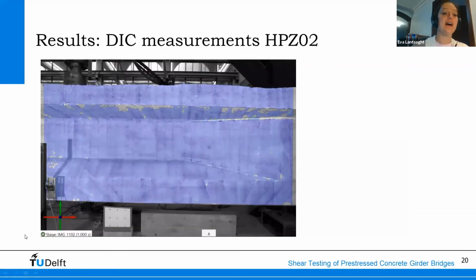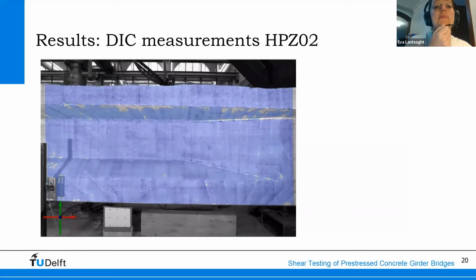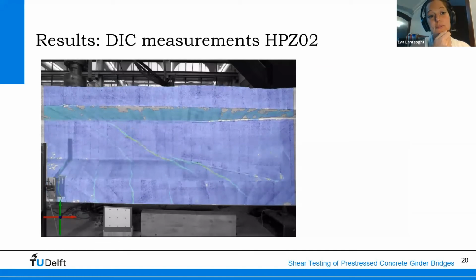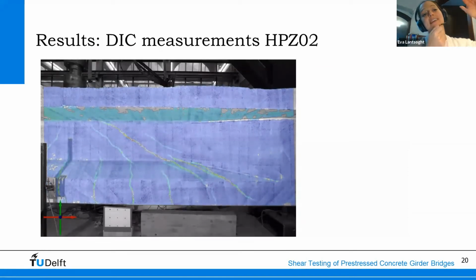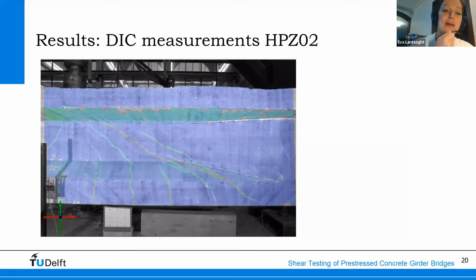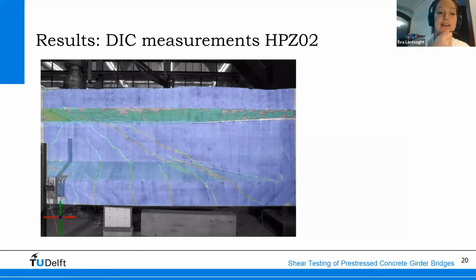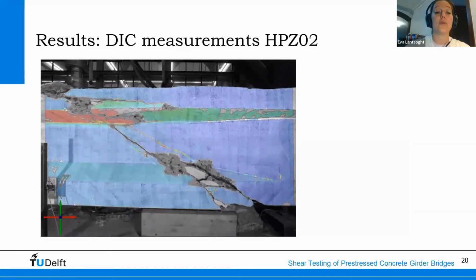Here's a video of some of the post-processing that we did based on the photographs that we then processed with digital image correlation. So you can see how the cracks develop. So you see first the flexure cracks, then the flexure shear crack, and then the development of the crack in the web along the shear tension crack or the web shear crack.